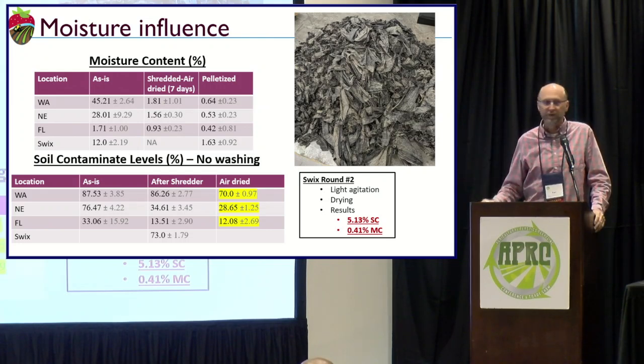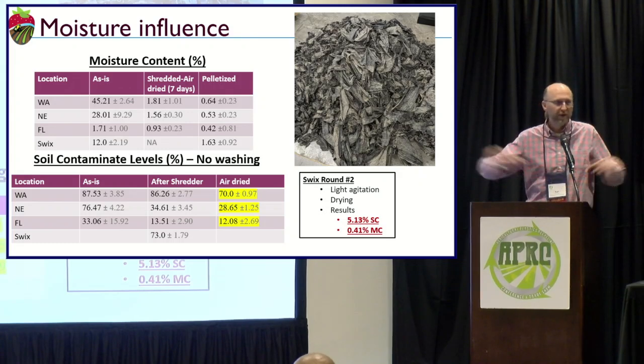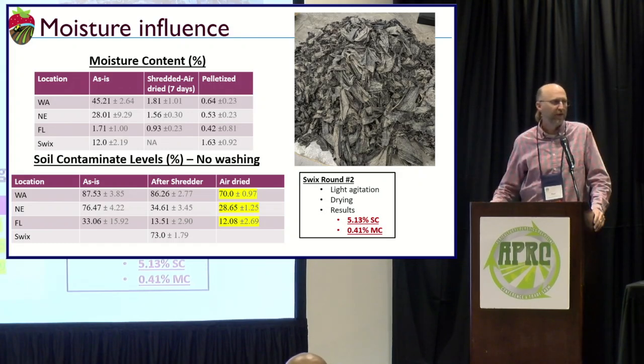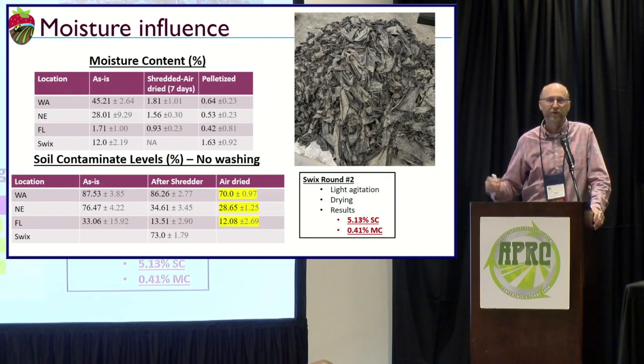The second round, we said, let's roll it out. We have enough space in our lab that we could just lay the bale out on the ground and let it dry for 6-7 days. Then when we go to process it and turn it into a pellet, let's pick it up and just shake it a little bit, and not try to pick up all the dirt and soil that came out of the bale. We got it down to about 5.13% soil contaminant, just by drying it and picking it up off the ground. That was pretty amazing in my mind, to get that kind of reduction just by drying it and letting it sit.